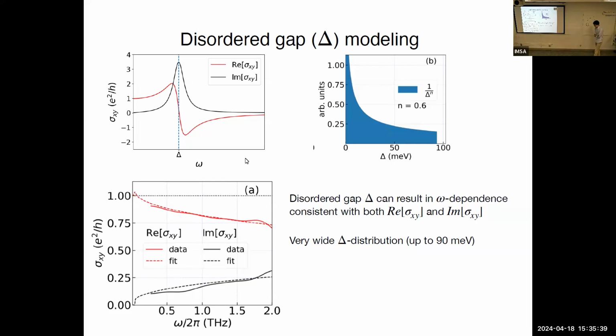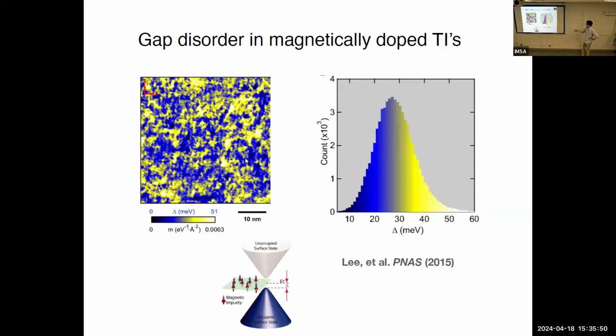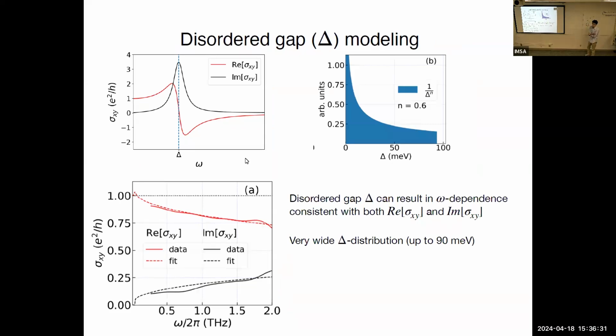So back to the point about mean field theory, the correct treatment would be to come up with some sort of mean field response. But as we saw here, mean field response, especially when it applies to optics, is going to be really dependent on the actual shapes and sizes of these small domains. So it's really not trivial to run a simulation which would be true for all the samples, because if you grow another sample, you might have the same overall distribution, but spatial shapes and locations are going to be different. And mean field theory would be giving you totally different things. So that's why we just decided to do what we are actually capable of.